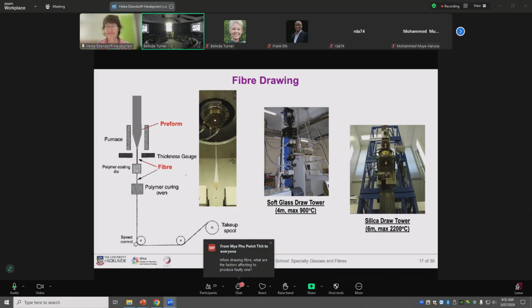Okay. Is that the one I just see there? Yes. Okay, so there's one more question perhaps, Heike, from online. When drawing the fibre, what parameters are important in determining its properties? So it's the drawdown ratio, which is the ratio between feed speed and draw speed. If there are holes in the fiber, then we can pressurize the preform to keep the holes open, or even to inflate the holes. The process control is done via this diameter gauge. And so then we can even have a feedback control loop, so that the drum rotation is adjusted so that the fiber diameter is maintained. So I think it's not many parameters, but they really have to be balanced in the right way to achieve the target structure.